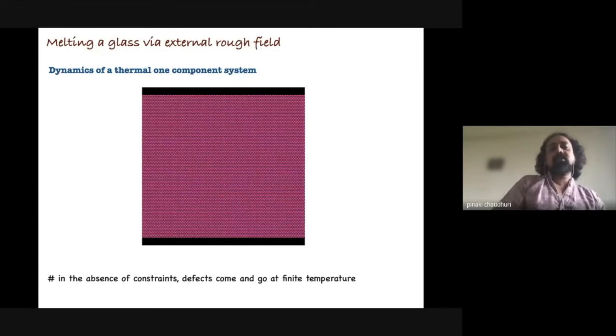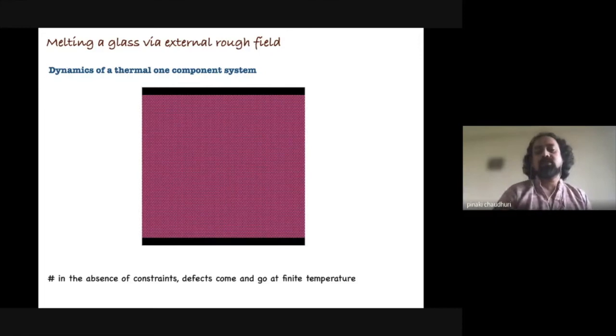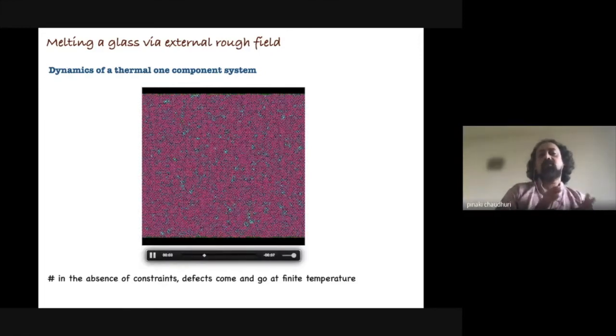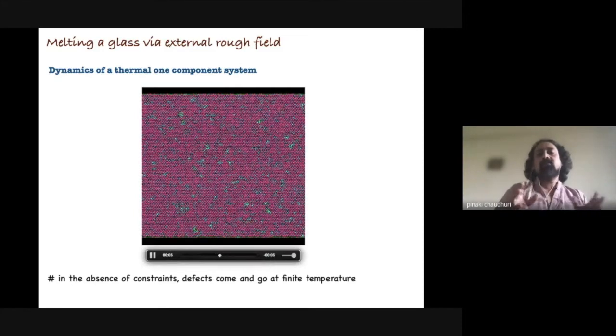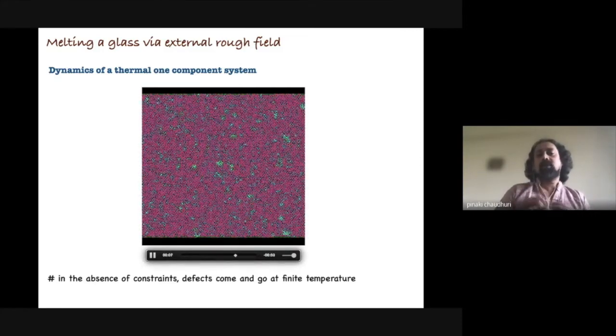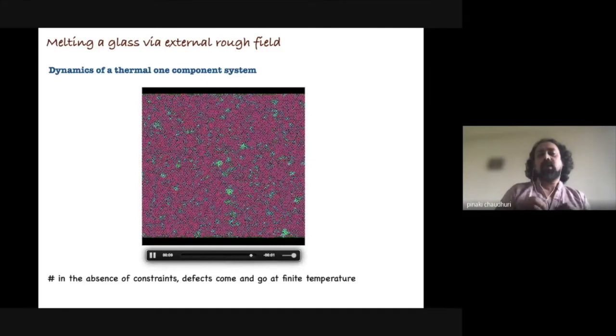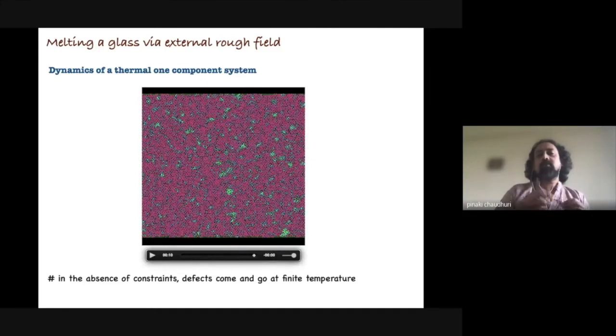What we have also recently studied is this: you had an ordered structure to begin with, and then if you introduce this external field which is rough, then at the end you have a disordered structure. So you can ask the question of how this ordered structure melts into this disordered structure. In the absence of any external field, at any finite temperature, you always have some thermal fluctuations happening, and certain defects are forming inside the system.